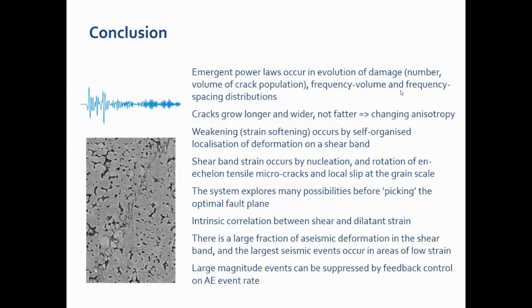Okay, so quite a lot of conclusions. We've got emergent power laws in the evolution of damage. That's the number of events and the volume of crack population, frequency, volume, and frequency spacing distributions. The cracks grow longer and wider, not fatter. That means we're going to have changing anisotropy. We see weakening by self-organized localization of the deformation on a shear band, and that happens very coherently, very quickly once you go over peak stress. And the shear band strain occurs by nucleation and rotation of en echelon tensile microcracks and local slip at the grain scale.